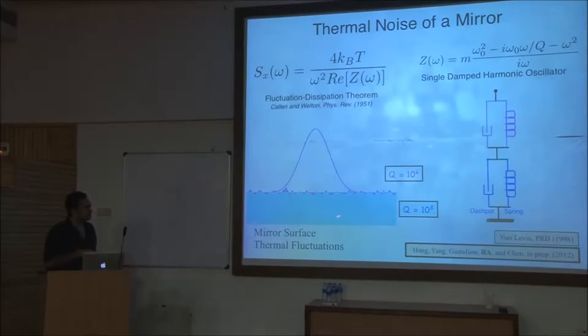And, yes, there is deformation throughout the bulk here, but if you look at this ratio of the actual Qs you get in these materials, there's no contest. There's basically, you know, to good approximation, there is no energy dissipated by straining the substrate. Just because people have worked so long to make the Q of these materials so good, there's almost no dissipation. And, a lot of dissipation happens on the front surface.